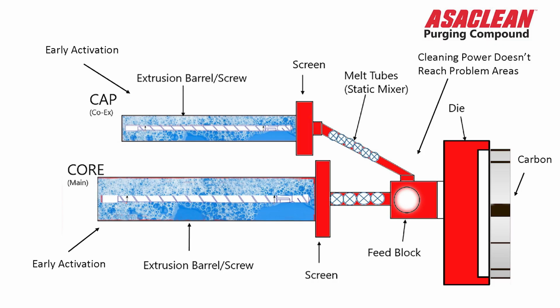So let's say we are purging an extrusion system. Typically in extrusion, we're not seeing a lot of the problems in the extruders themselves. They're always downstream: melt pump, static mixers, die, feed block. Those are the areas where we're going to increase heats. So in the extruders, we would keep those at operating temperatures and increase heats where we need to, because we don't really want to set the purge compound off to its maximum capability in the extruders where you don't need it. We want it to happen downstream. So that aids in the cleaning process extensively.